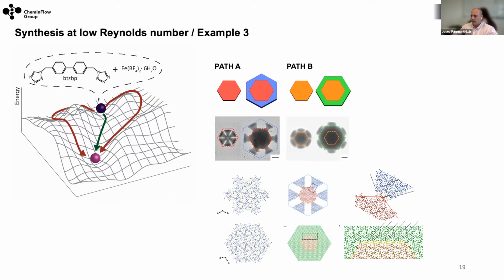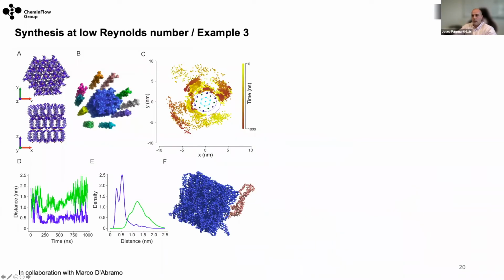So we submitted this publication, but no one believed us. They didn't believe that was the case, and they even doubted that this was real. I mean, you can clearly see that the growth is different here, because you have a shift of 30 degrees there, whereas here it is just parallel, right? So we decided to do full atom molecular dynamics simulations. What you see here is a cluster of 19 strands of this coordination polymer, and then we have 10 extra strands around this cluster made of 19.